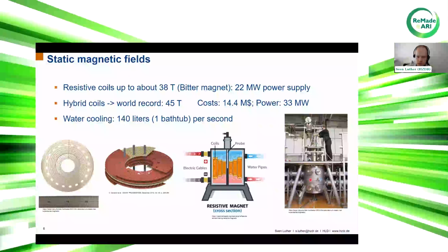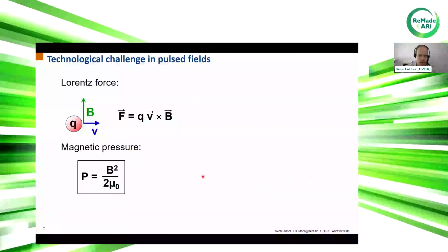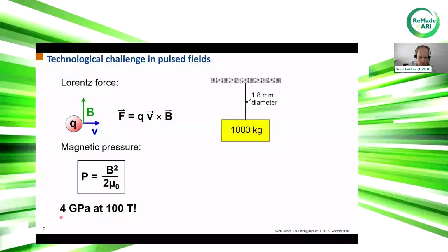And if we want to go to much higher fields, we have to use pulsed fields, and there we have different technological challenges. As maybe some of you know, we have Lorentz forces acting on the wires, which are perpendicular to the velocity of the electrons and to the magnetic field. From these forces we have a magnetic pressure, which goes with the square of the magnetic field, which means if you double the magnetic field, you already have 4 times the pressure acting on the wires. And at 100 Tesla, we already have 4 gigapascal. You can imagine this as a wire of 1.8 millimeter diameter with a weight of 1,000 kilograms hanging at the end. That's the pressure acting on this wire.